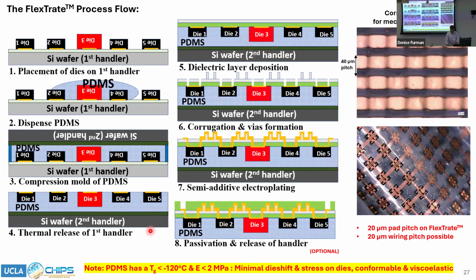One of the key innovations here is the use of PDMS, because PDMS has a glass transition temperature less than minus 120 C, which basically means that PDMS can be cured at room temperature. It also has a Young's modulus less than 2 megapascals, which means during the curing process, it doesn't exert much stress on the dies. And so the dies don't shift much during the curing process and also during operation. This improves both the mechanical reliability of the package itself and also allows us to make fine pitch wiring on this substrate. So what can you build with this?